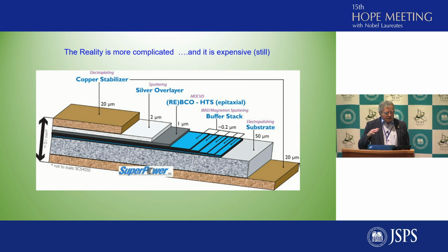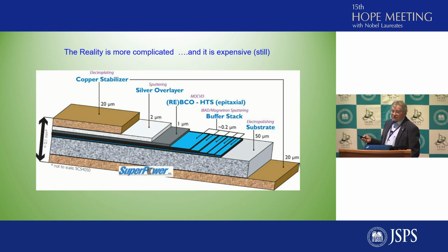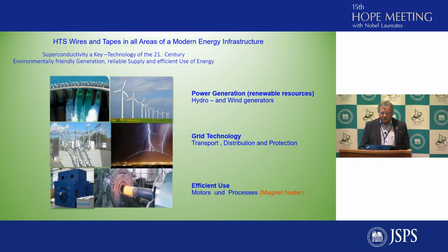Here we have 1 micron, but you can design your cables or your tapes with a varying thickness of the superconducting layer. But 1 micron is already able to have several hundred amps passing through this composite. So the total combination of all these layers is of the order of 0.1 millimeter. So you have still a lot of flexibility in this composite materials. So this makes the high temperature superconducting wires very interesting for application in all areas of a modern energy infrastructure.